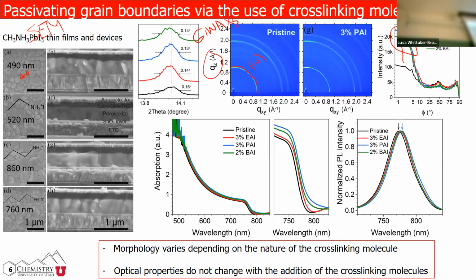Because we don't want those to change as a function of us tuning or mucking around with the morphology, okay? So we know that there's not a change in the absorption. They have basically the same band gap. The PL signal is basically the same. So we know that we are not changing the optical properties by changing the morphology.